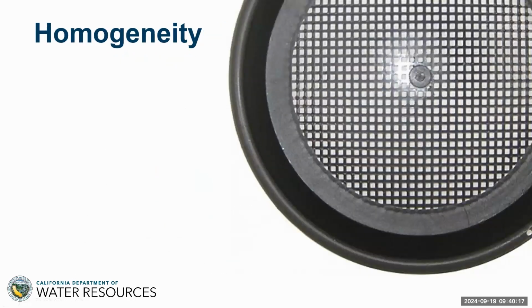Homogeneity, a fancy word for saying we don't want any lumps in the grout. And this is going to be reflected in the kind of mixer that we use. For example, if we use a paddle mixer, which we'll discuss later, the Corps of Engineers recommends putting the grout through this 1/4-inch sieve to make sure that two things happen. One is that no lumps go into our grouting system and therefore cause blockages. But of course, if we do have lumps that are retained by the sieve, that means that the material that's gone through the sieve has a different water cement ratio, i.e.